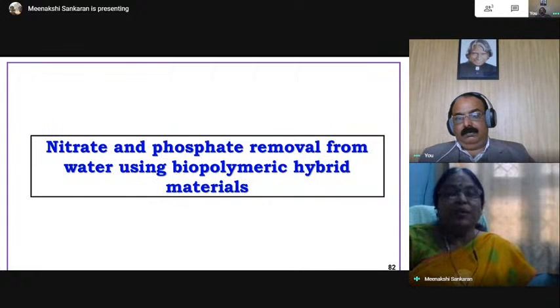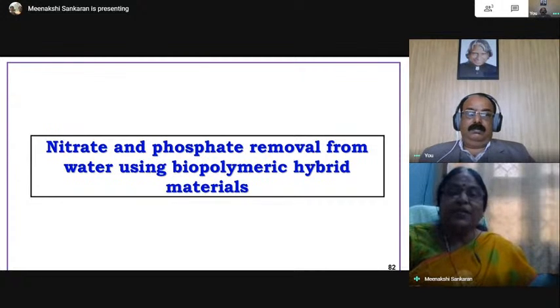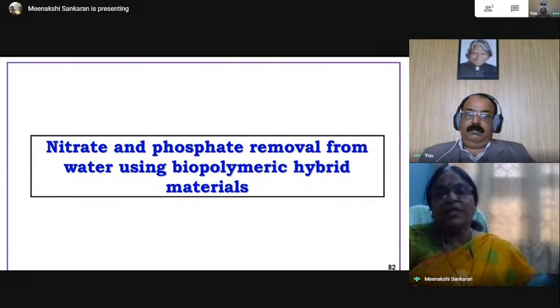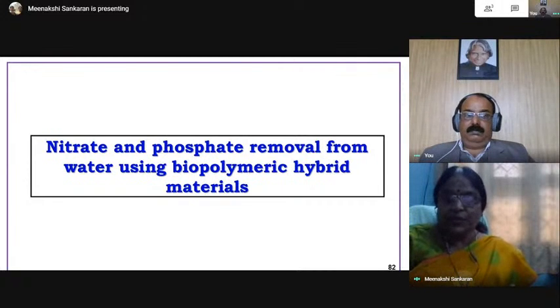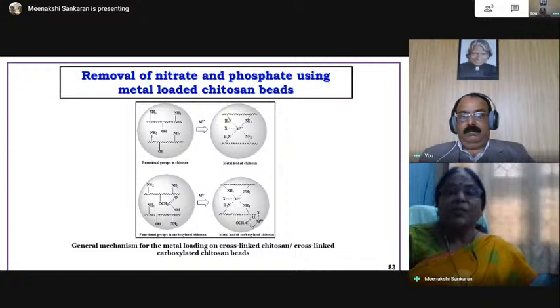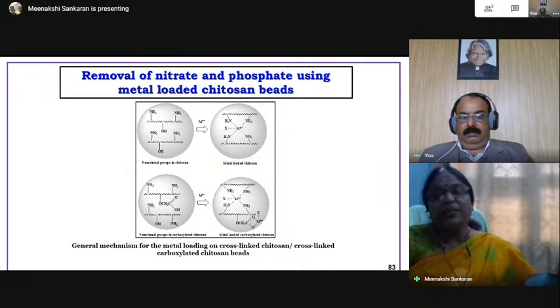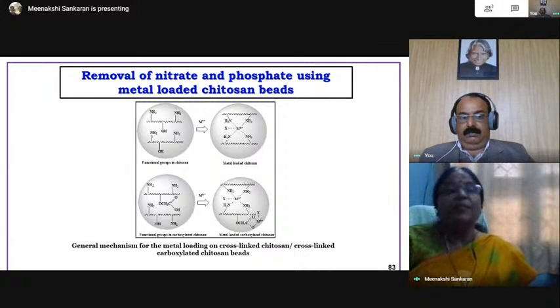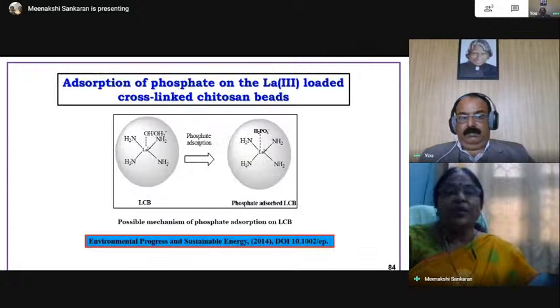So again, we have used biopolymeric hybrid materials, that is inorganic and organic material, chitosan and some inorganic material we have blended. Composite hybrid materials we have used, and chitosan as such we have used. So nitrate and phosphate removal we have done using metal loaded chitosan beads. Nitrate was removed by means of ion exchange mechanism, and phosphate was removed by complexation mechanism. This is the general mechanism. Accordingly, we have modified our material. And this is lanthanum 3 loaded cross-linked chitosan beads. This lanthanum forms a complex with the phosphate and thus removes it.